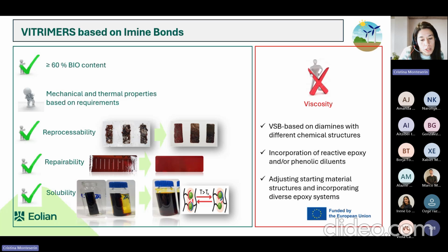Additionally, the materials show good solubility, which is very beneficial for recyclability. But we have to say that we are still facing some challenges, such as viscosity, for example, which remains an issue for processing. To address this, we have different strategies that we are working on. For example, we are investigating vanillin-based diamines with different chemical structures, as well as the incorporation of reactive epoxy and phenolic diluents. And also we are adjusting the starting material structures and incorporating diverse epoxy systems to further optimize the material properties. Overall, these results demonstrate both the potential of the bio-based vitrimers and the ongoing strategies to improve their performance.